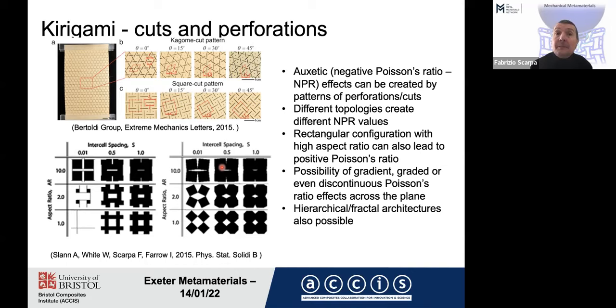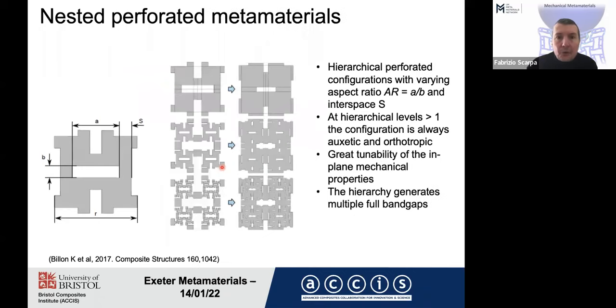You can also tessellate gradient configurations. And it's possible to construct hierarchical fractal architectures by using this type of Kirigami cut approach. And I chose here an example of a nested perforated metamaterial that we published some time ago. We take the central square pattern perforation that was first identified by Ole Sigmund via topology optimization more than 20 years ago. If we repeat the same pattern on the rotating rectangles that we see on the four sides of the unit cell at different levels, we can recreate this type of nested or hierarchical configuration.